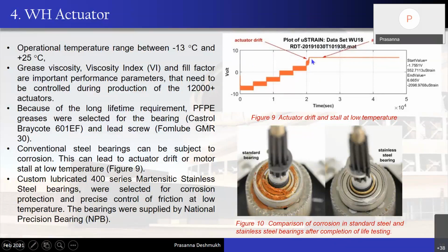So, to get very good protection against such problems, we use something called PFPE greases, which are manufactured by Castrol (Braycote) and Fomlube. These greases were used in the bearing as well as on the shaft, which was previously made up of a special Teflon coating. But further, we also noticed that the Teflon coated shafts were giving away small particles which get mixed with the grease, and we were experiencing added friction within the motor. I'll show some images for that as well.